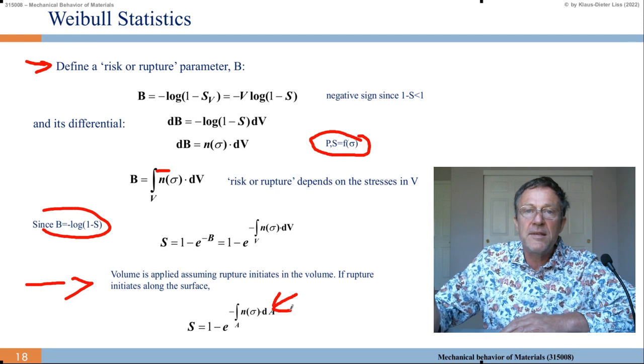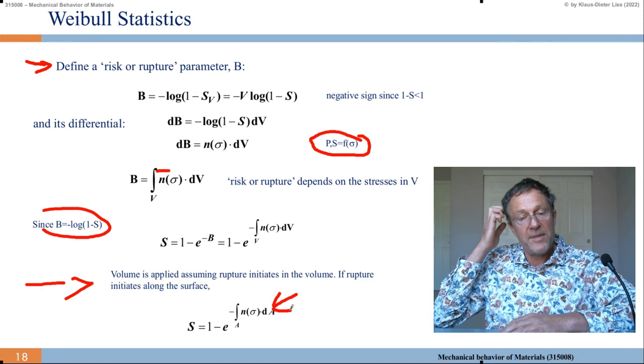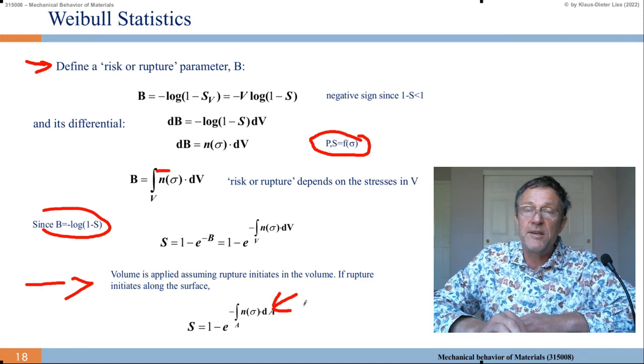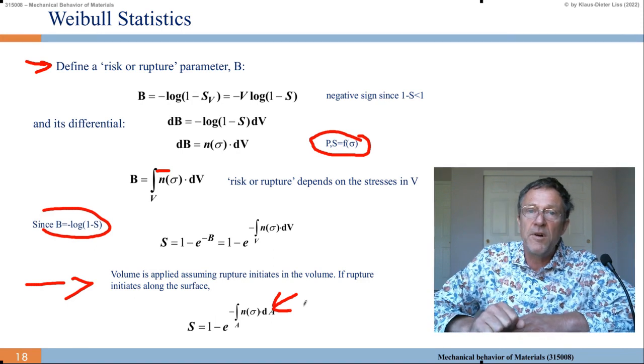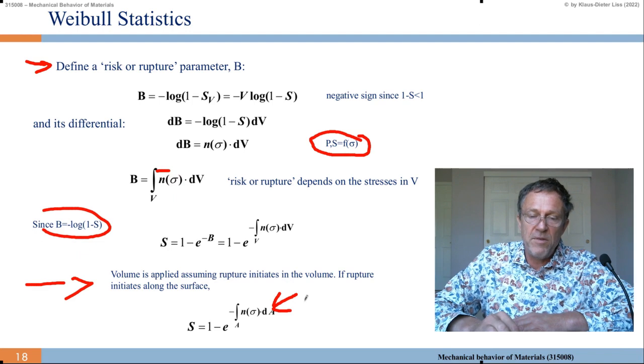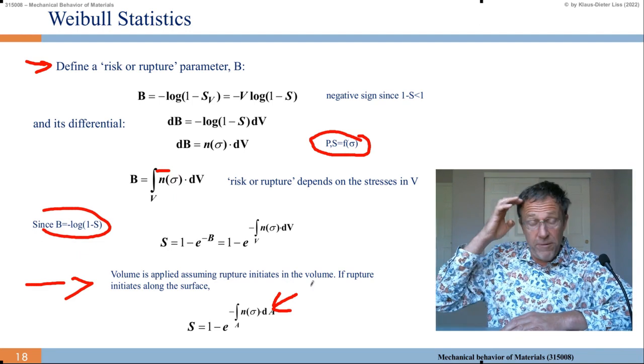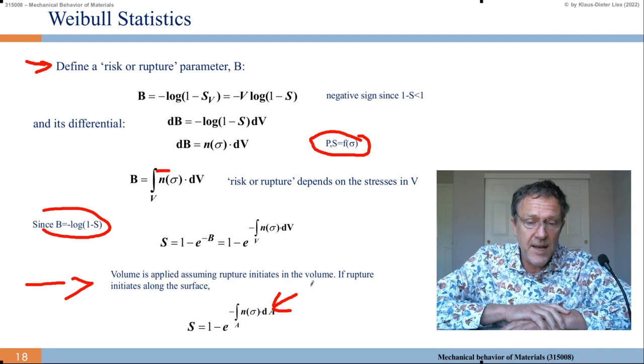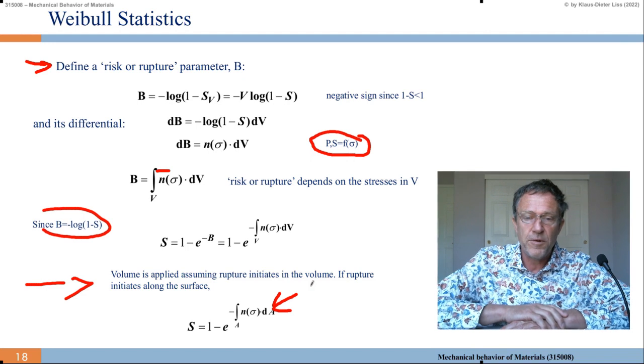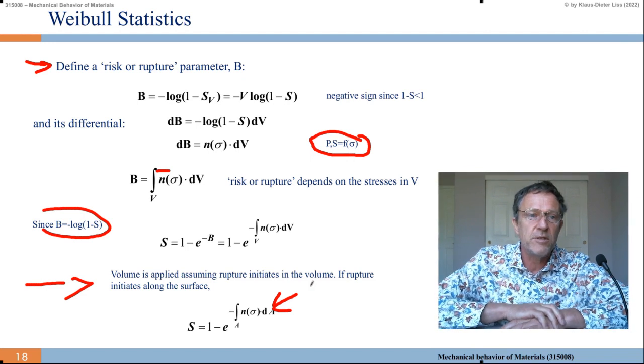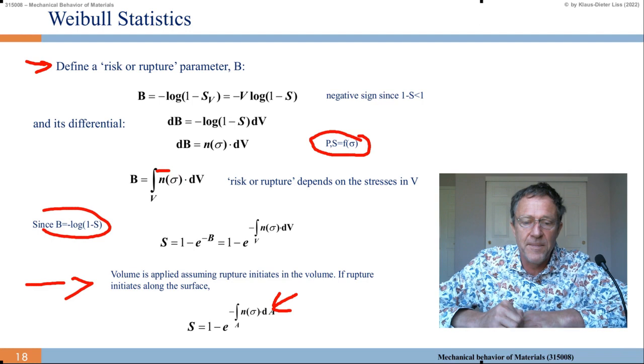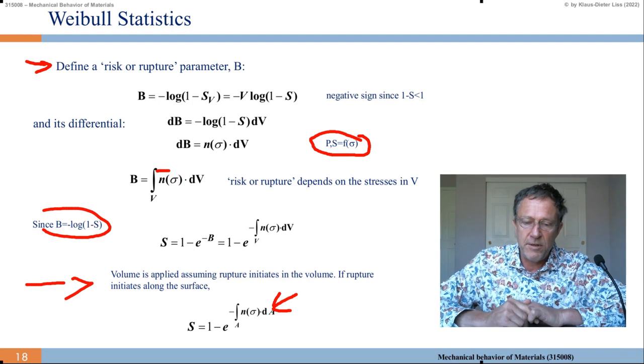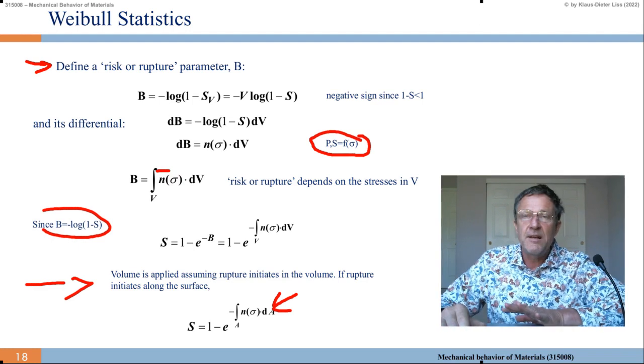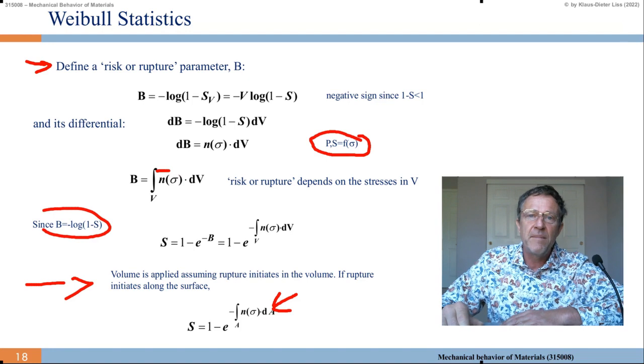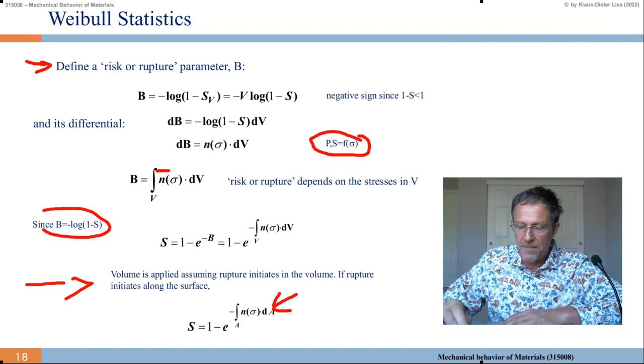So it depends on the model where the failure initiates. If it initiates in the volume by inclusions, then we put the volume in. If we say there's no nucleation of cracks within the volume, but only at the surfaces, surface roughness and so, then we integrate over the surface. So it's a slight modification of the formula, but the formalism behind is the same.